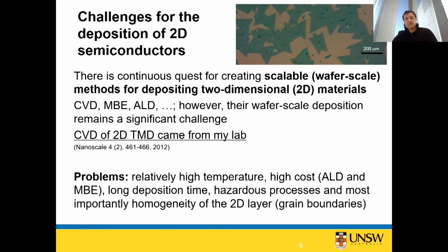Everybody is claiming that we can make this material on wafer scale, on, for instance, silicon dioxide substrate, and make transistors from this 2-dimensional based transistor. But the reality is, if you do chemical vapor deposition of this material, again it becomes a classical nucleation deposition. That means you must have nucleation points, and these 2-dimensional materials grow out of those nucleation points. The center is not 2-dimensional material.